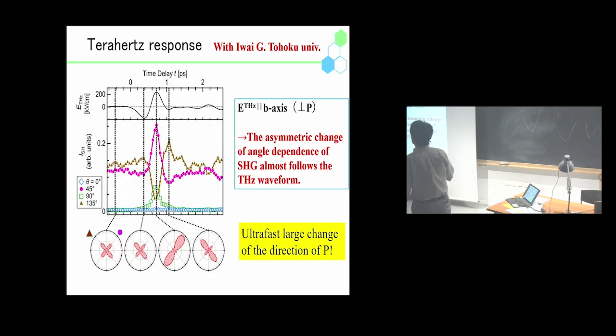Finally, I will show you the time dependence of the azimuth angle dependence of these crystals, ytterbium Fe2O4. At this point, we observe the largest change. You can see the asymmetric change of the angle dependence of the SHG almost follows the terahertz waveform. So we can conclude that this electronic ferroelectric material shows an ultrafast large change of the direction of P, as well as the magnitude of the polarization. This is the conclusion.